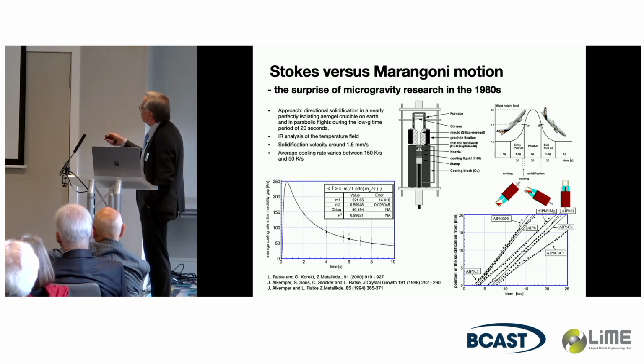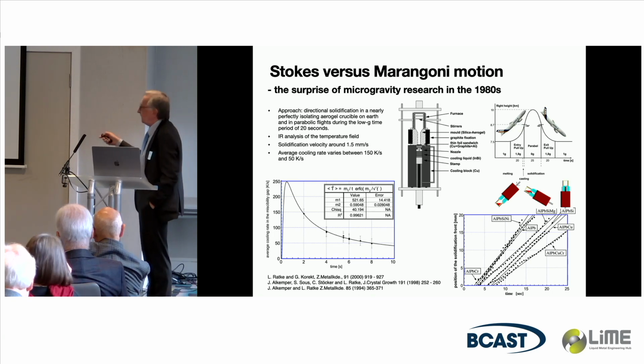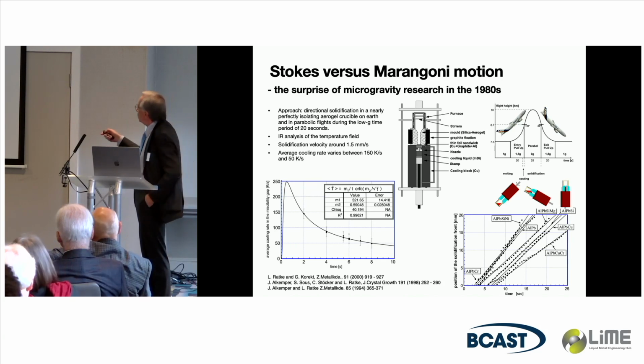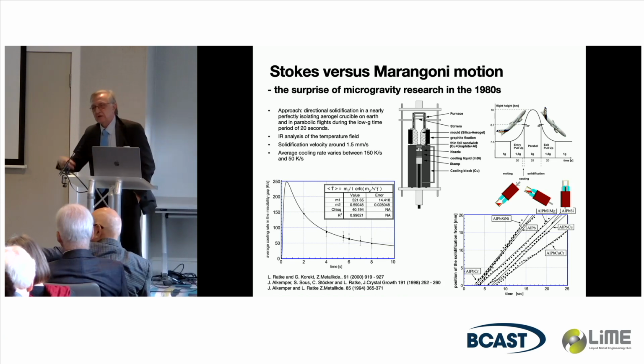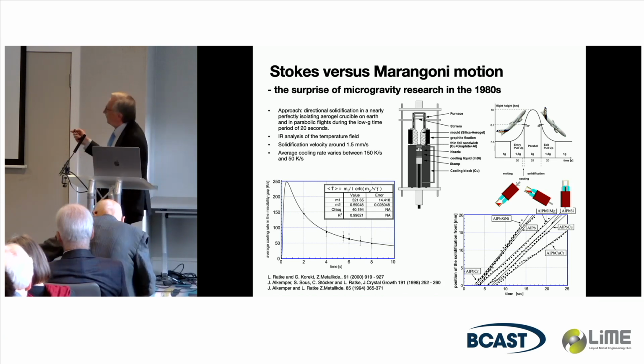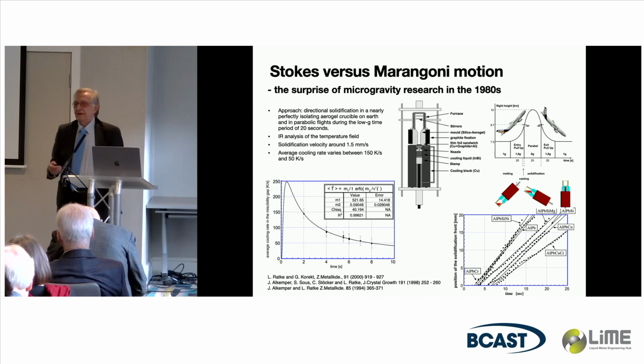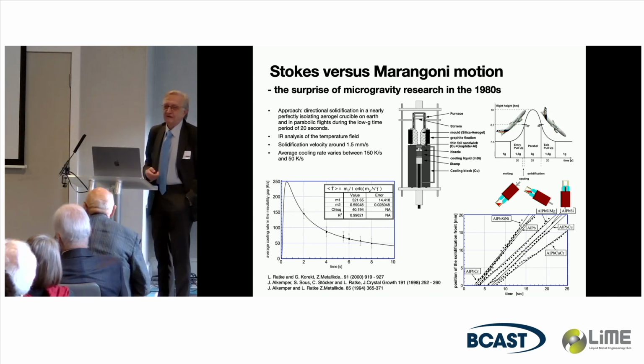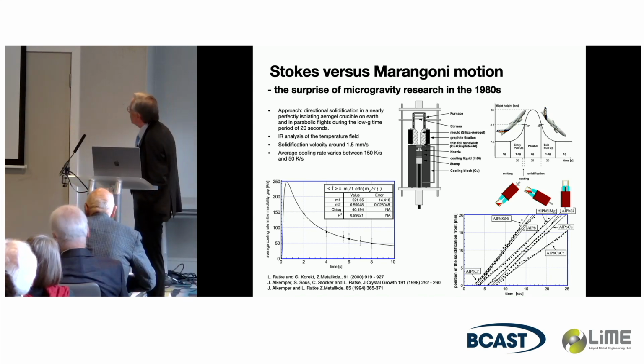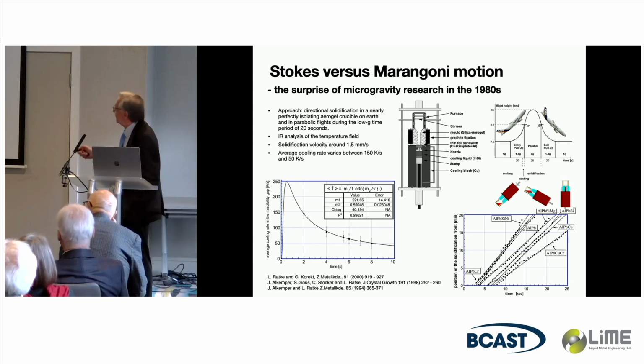And in parabolic flight, you should say the plane is up to around 7.5 kilometers in height. It's 1g, then it enters up in a 2g phase, and then it flies a free fall parabola for around 20 seconds, something like that, 10 to the minus 2g, and then it comes back, and you do that 30, 40, 50 times again. So one calls it vomit comet. In a certain sense, this is not incorrect. And how do you do then a casting?